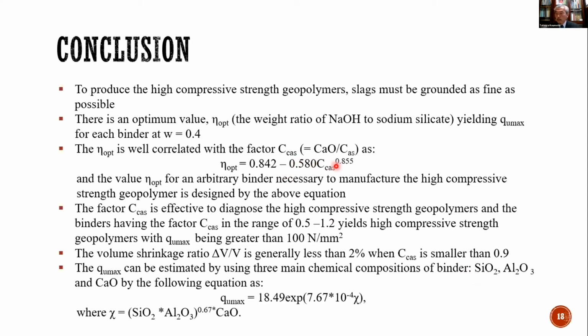And the value ηopt for an arbitrary binder necessary to manufacture the high compressive strength geopolymers is designed by the above equation. The factor Ccas is effective to diagnose the high compressive strength geopolymers, and the binders having the factor Ccas in the range of 0.5 to 1.2 yield the high compressive strength geopolymers with Qmax being greater than 100 Newton per square millimeter. The volume shrinkage ratio, delta V over V, is generally less than 2% when Ccas is smaller than 0.9. The Qmax can be estimated by using three main chemical compositions of binders by the